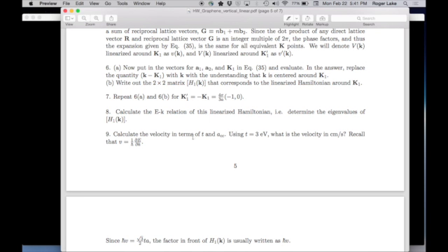So you'll compute this, and it should come out to, I guess, something on the order close to, what did we say last time? 1/300th the speed of light. Something close to 10 to the 8 centimeters per second. Maybe a little under, like 9 times 10 to the 7th or something like that.